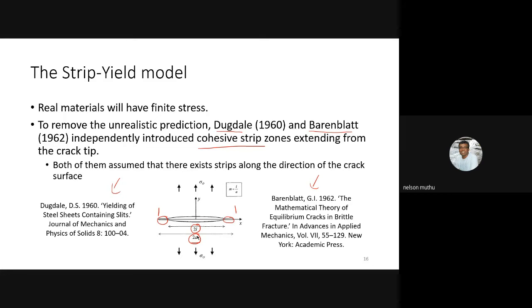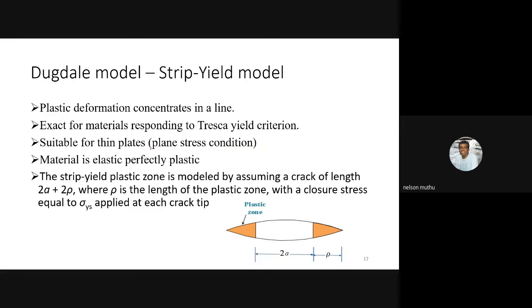So now how do we find this strip length? They assumed certain things. As I said before, it is another perspective of looking into things to bring in this plastic zone correction factor so that we can still use LEFM principles. These are the assumptions they had. Plastic deformation concentrates in a line. So there are two strips at either end of the crack tips. It is essentially a central crack inside an infinite geometry. The plastic deformation is only confined to the strips, and it is suitable for thin plates. That means they derived this model only for plane stress scenarios, and the material is again elastic, perfectly plastic. It has been found that the materials respond very well to the Tresca yield criterion.